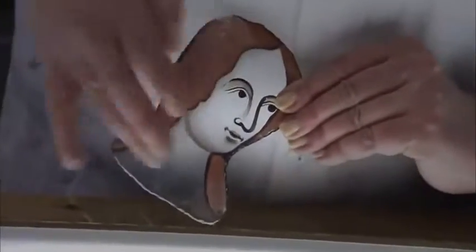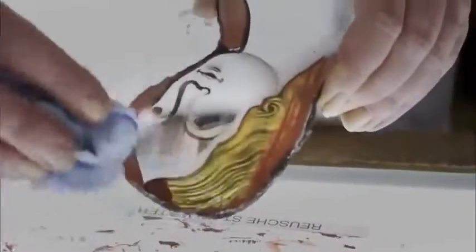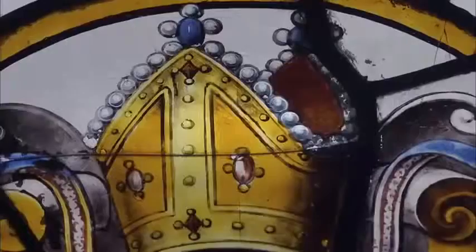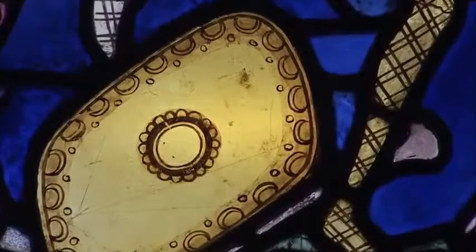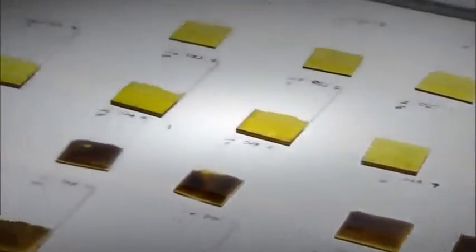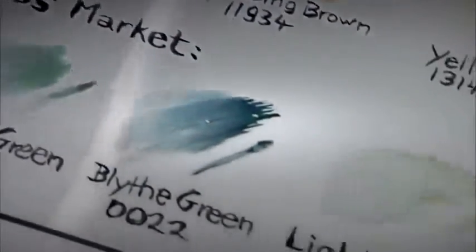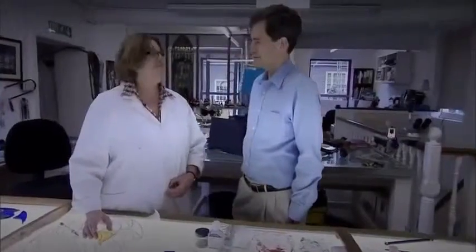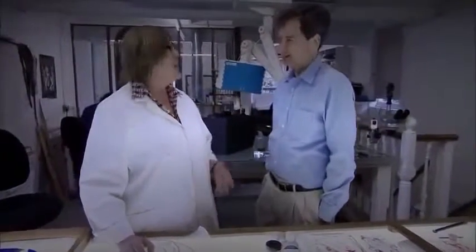The trouble is that you don't just paint a yellow color on glass and you know how deep and how rich it is. You have to use a chemical process. So to make yellow, you mix silver with clay. Silver under heat actually produces a yellow glass. She's using silver chloride, which in its natural form looks like small silvery crystals. Leonie mixes a tiny amount with red clay. It's a silver salt that is mixed with this clay. I get it. You can't see it. What you see is the clay. You would then paint that on. I've made a little series here where I've now applied this clay and after it's fired if I then wipe that off. And hey presto. Look at that. From silver clay comes a golden color. There's some kind of voodoo chemistry going on there for sure. That's the mystery. Somehow, this is nanotechnology at work. In the heating process, the silver crystals break down into tiny nanoparticles and turn yellow. But it only works on this glass.